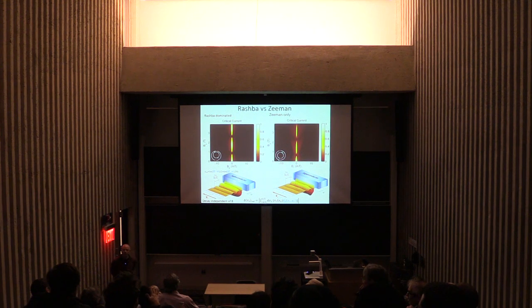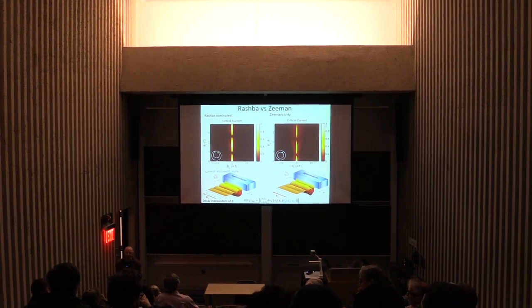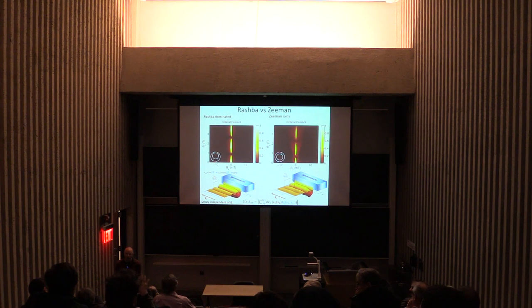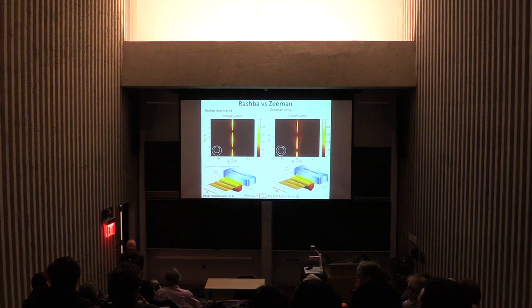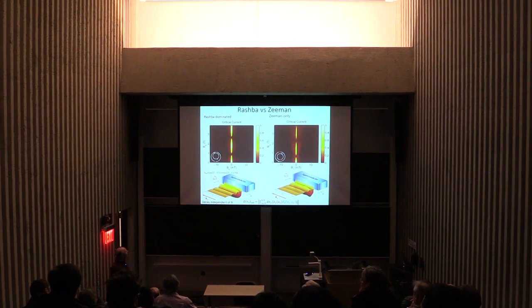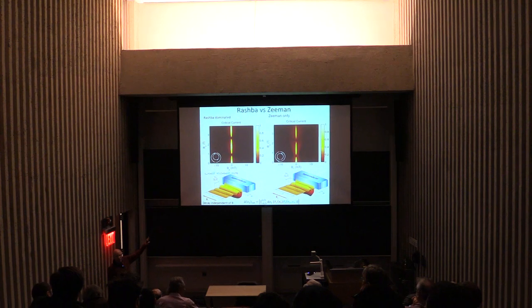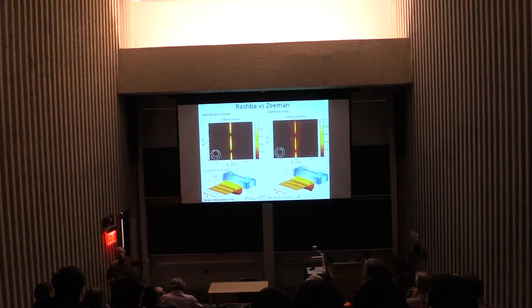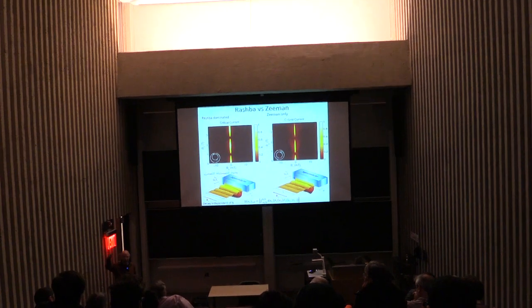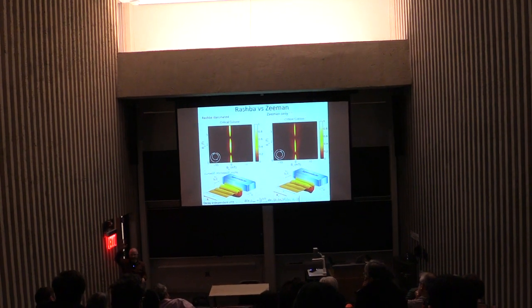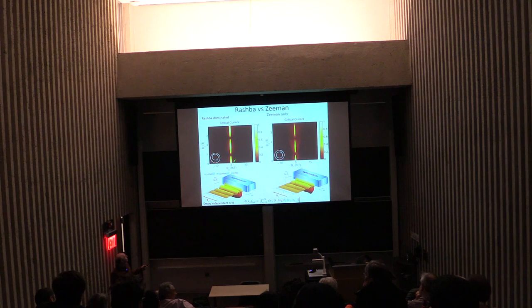I guess in the FFLO state you don't see a very clear Fraunhofer pattern, in the higher magnetic field. Is there a reason that gets washed out in that state? Yeah, so I focused only on the experiments in aluminum. We've done the same experiments with niobium, where you do see very nice Fraunhofer patterns at higher magnetic field. There's a little bit of jitter that takes place. It's not entirely clear to us why the intensity of the critical current dies off as you increase magnetic field. In this geometry, theory tells you if your geometry is perfect, you should get no decay.